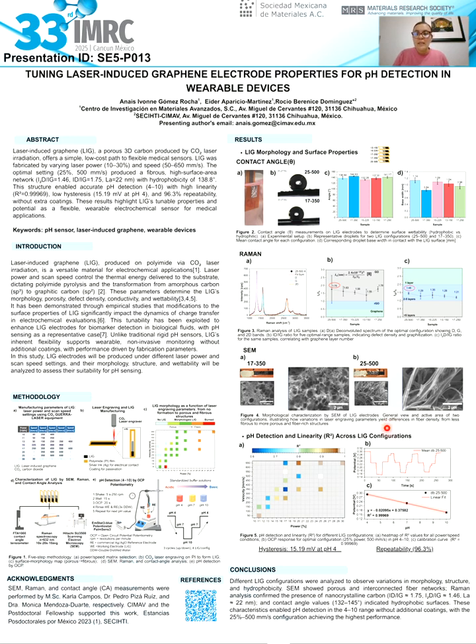We test in standard buffer solutions of pH 4, 7, and 10, always following the same routine. First, we place the electrode in the solution, stay for 5 seconds, and then rest for 15 seconds to stabilize. After that, we record the open circuit potential for 20 seconds. Once finished, we rinse the electrodes 3 times before moving to the next pH. We repeat the process for 3 full cycles. Okay, now the results.